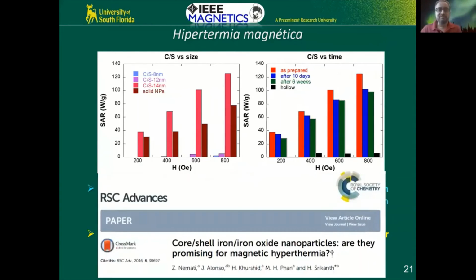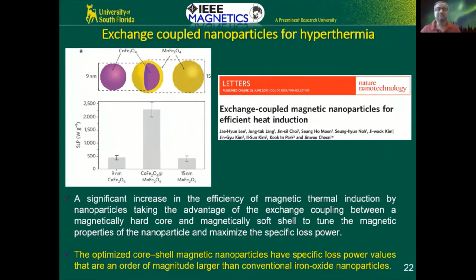And this is when we found this paper. This was back in 2011. There's a group from Korea, a very good group, that published a paper in Nature Nanotechnology showing that if you have core shell nanoparticles of 2 different ferrites, in this case cobalt ferrite and manganese ferrite, there is no Kirkendall effect because it's not metal and oxide, both of them are oxides. So it's all oxide core shell particles. And they actually showed that the SAR is very high.